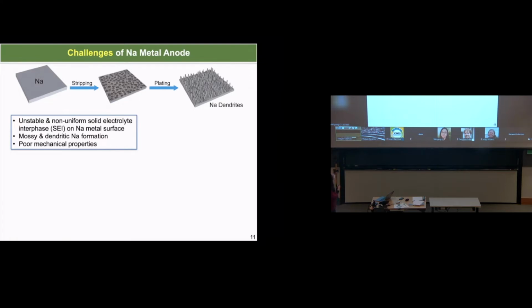During the stripping and plating process, there is a series of challenges related to the sodium metal anode. One of the biggest challenges is that during this charging or discharging process, you will have an unstable, or we call it non-uniform, solid electrolyte interface formed on the sodium metal surface. This means that there is a thin layer of material formed during the charge and discharge process on the surface of the sodium metal anode. However, this thin layer is not very stable over the long-term cycling of the sodium metal anode.